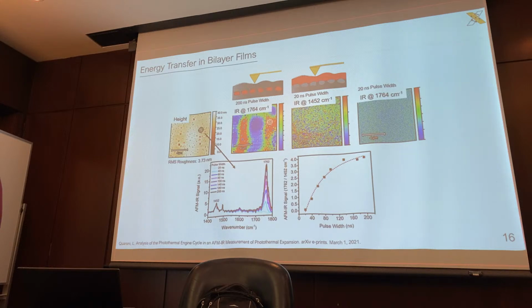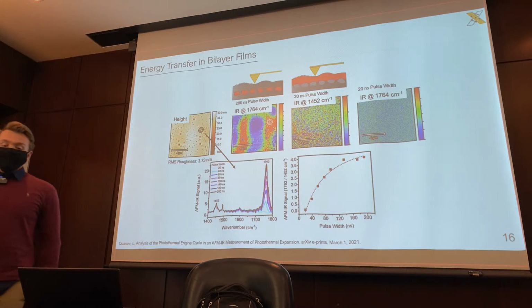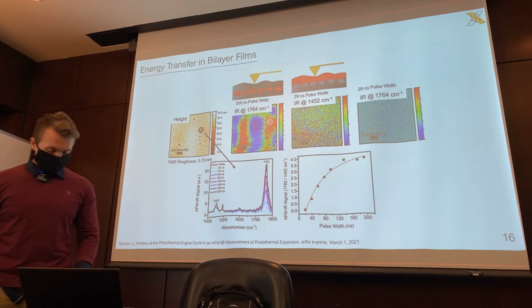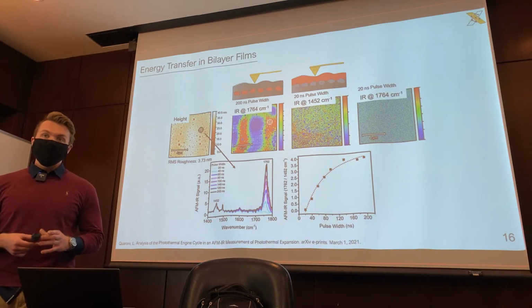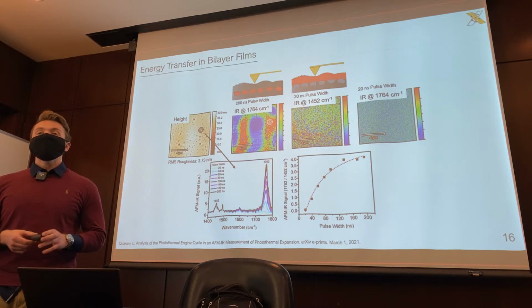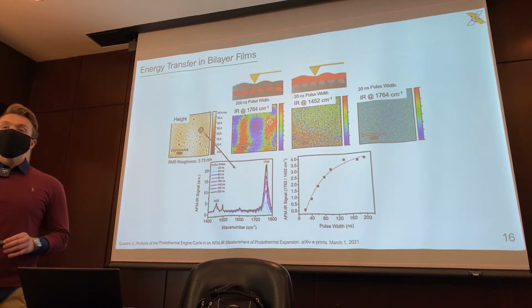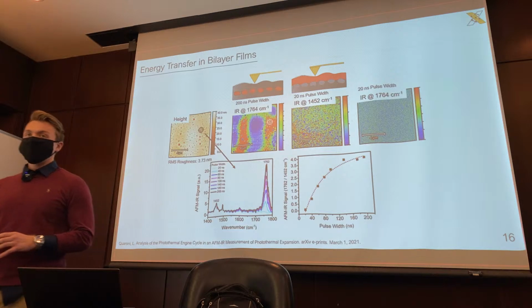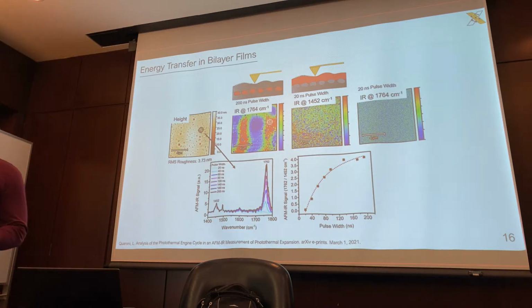Interesting. I wouldn't be as interested in reflection. I would be more interested in, does the silicon heat up at all locally? It also is going to disperse heat very quickly compared to the polymer. So maybe it doesn't matter. Right. But I was just thinking, is there an additional thermal lag where the silicon is actually heated and it keeps the polymer from decreasing in thermal expansion? You're going to see that more often with thicker samples too. Or I should say, you'll see a lot more of that thermal loss in the bottom in the polymer.